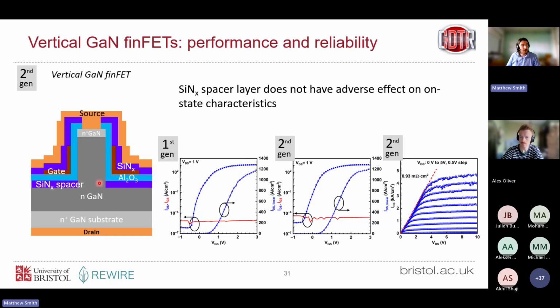So there may be a bit of a drop in mobility as a result of these processes, but there was a paper from Thomas Palacios' group a few years ago which showed the contribution to the total resistance of the device from this fin is, if I recall, in the sort of 5-10% area. So any changes to mobility here are fairly negligible, which to be honest is a shame because there's a lot of interesting things you can do in this region in terms of optimizing the mobility. But it does look like the major drawbacks from this first and second generation were trapping effects and stability rather than on-state performance. So I can't tell the exact mobility there, John, but one thing we are doing is trying to develop test structures which can help us to extract properties of these fin sidewalls directly. Maybe we can talk more about that offline.